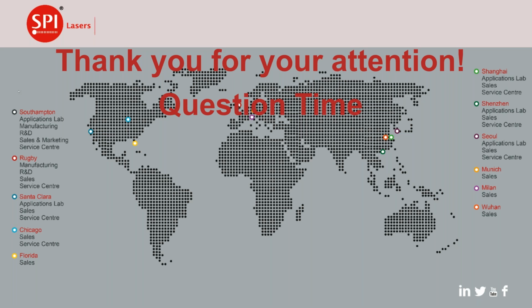So as I was showing in the presentation, aluminium, for instance, works better with a slightly larger spot size, even in single mode. And we did that using a different scan lens focal length. But copper works very well with a small spot size for the same laser power. So the lower power density on aluminium works better, gives a better cosmetic weld. And for doing that, you could indeed use a larger diameter multimode fiber. Part of the reason why we've concentrated most of the work on single mode is that it gives you the greatest flexibility, because you can use it for a number of different materials. The same laser, the same setup can be used across a wide range of materials. And then you use the scanner as the flexible programmable device to change the weld conditions.